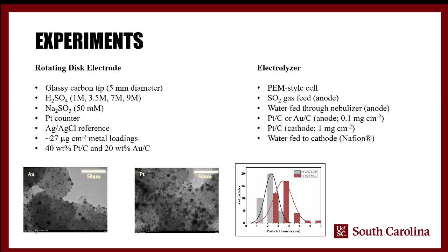The loadings of the catalyst that we used for both platinum and gold were 0.1 milligrams per square centimeter of metal on the anode, and we kept a consistent 1 milligram per square centimeter of platinum on the cathode. That's more than enough loading to ensure that the cathode is not a limiting factor for the reaction. So we know that any difference that we see in cell performance of the electrolyzer is due to the difference in the catalyst that's on the